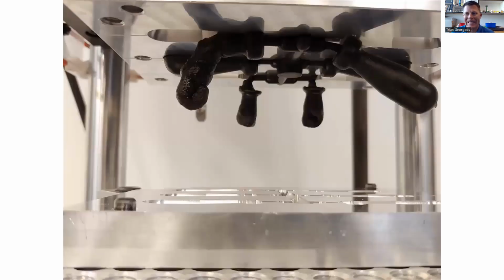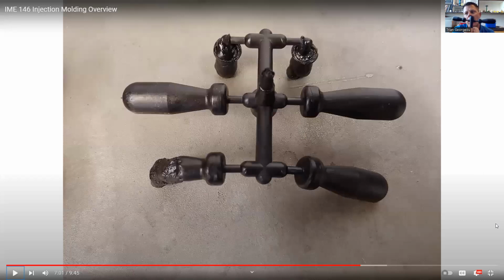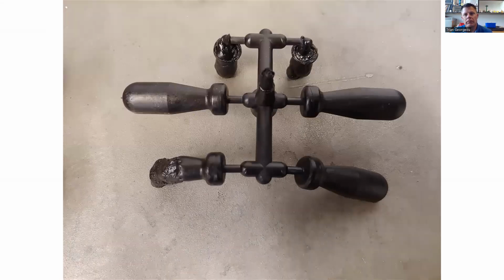In this case, we have an underfill, which means that our mold did not fill completely. There are some usable parts, but not all of the parts are usable. When we had 6, we were having a lot harder time. When we just inject 2, it's a lot easier for the melt. This can be due to many factors such as barrel and nozzle temperature, mold temperature, injection time, injection pressure, too little material in the material chute, cycle time, and or time between injection events.